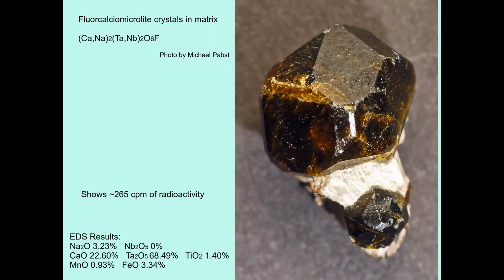Now, in this photograph, this shows some slight degree of radioactivity. Turns out all samples of microlite group species are slightly radioactive, even though neither uranium nor thorium showed up in any of the EDS test results. As reported earlier by Glass, this is because they're generally zoned and metamict. This sample was interesting because of the lack of detectable niobium, as you can see at the bottom there. Later in the presentation, I will show why most of the slight radioactivity was probably due to the presence of thorium rather than uranium. Next slide.